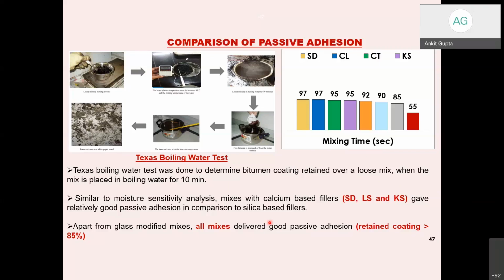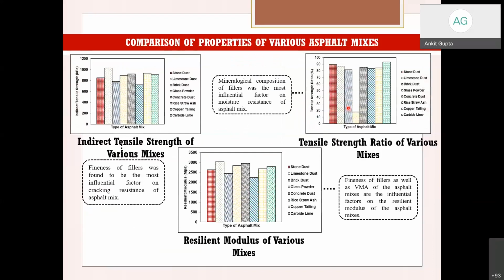Again you'll see that as compared to the stone dust, every value is almost similar. Only the problem is with the glass powder. Again, the retained coating should be more than 85%, and it was shown by most of the fillers.